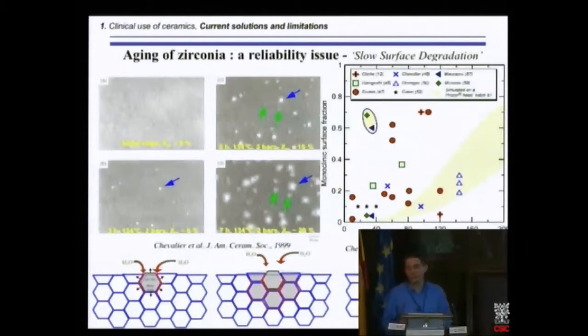So what is happening now in vivo? That's most important. Here is the monoclinic surface fraction, so the amount of aging of zirconia. Tetragonal to monoclinic transformation means aging, means degradation of the surface, versus time in vivo. What we expected in some batches from this accelerated test was here.